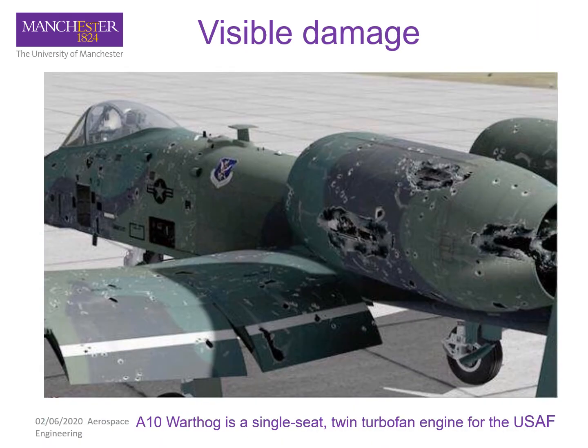We have spoken about that invisible damage and the mathematical equations that will enable us to optimize the properties of the constituents, to optimize the laminate stacking sequence, and derive expressions that will enable the designer to estimate the critical stresses at which matrix cracking or delamination or fiber microbuckling will be triggered, how much energy is required to initiate those damage mechanisms in order to develop systems that are damage resistant.